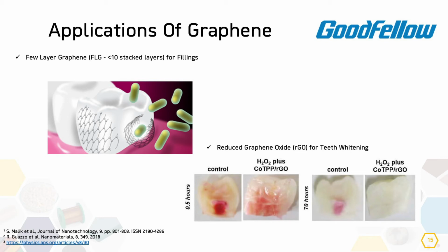In addition, I saw this one, that graphene can be used for teeth whitening, which was very interesting. And the reactions that you can have with cobalt tetra, I hope I will say it correctly because it's a little bit tricky, this one. The cobalt tetraphenylporphyrin with hydrogen peroxide is enhanced because of the high surface area of graphene. And we can whiten our teeth in less than 70 hours, as we can see.